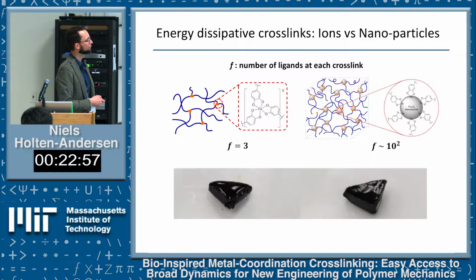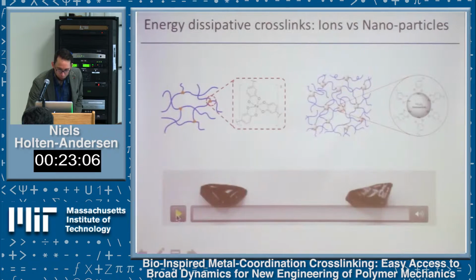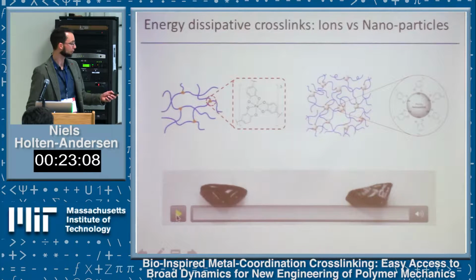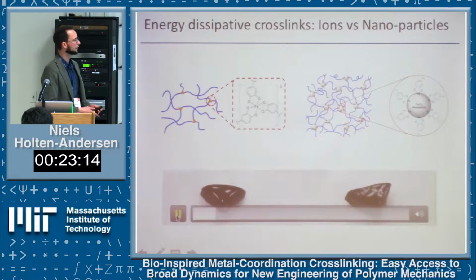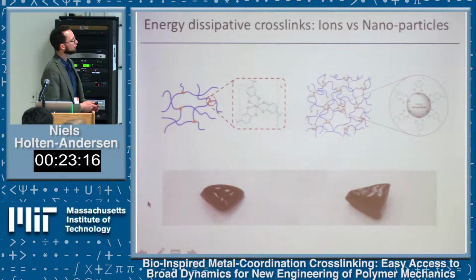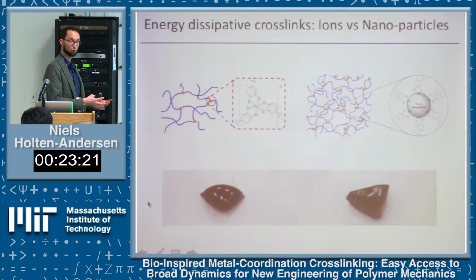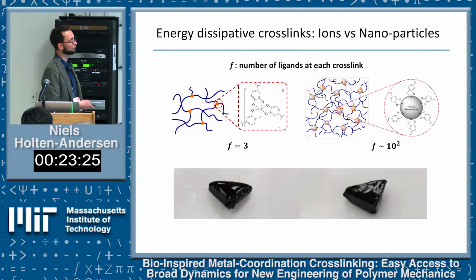So again, this is the basic idea: metal ion as a cross-linking species in the network, or nanoparticle. This is just a little video showing two different gels at room temperature, sped up a little. This gel is held together with metal ions, this one with nanoparticles. You'll see that at room temperature, this one will basically curl into a little drop due to surface tension, whereas this one will hold its own shape because it's cross-linked with nanoparticles.